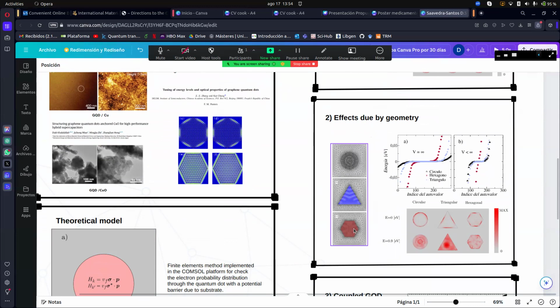The first with an infinite potential, representing an isolated quantum dot without any substrate outside of it. And the second one with a potential of 0.2 electron volts. The results reveal significant differences in the energy values of the wave function. Without a substrate surrounding the graphene quantum dot, the three symmetries exhibit relatively similar behavior, with the main difference being the energy values they present.